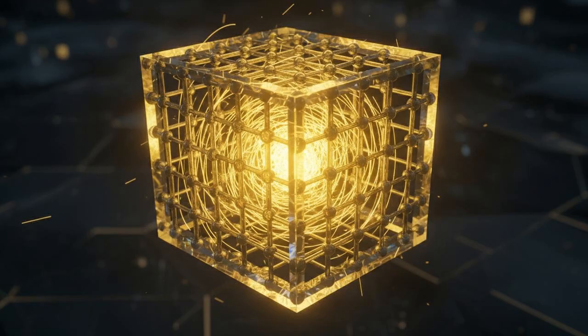And we cannot talk about next-generation materials without mentioning perovskites, the three-dimensional and two-dimensional miracle materials. Organometal halide perovskites have taken the photovoltaic world by absolute storm, soaring from single-digit efficiencies to over 25% in just a single decade. Their secret lies in their unparalleled ability to generate highly mobile charges with exceptionally slow recombination rates. When examining materials like two-dimensional cesium-lead bromide nanoplatelets, researchers using transient absorption spectroscopy note that efficient charge separation can be achieved by transferring electrons and holes to adsorbed molecular acceptors. The half-life of these charge-separated states can exceed 100 nanoseconds.